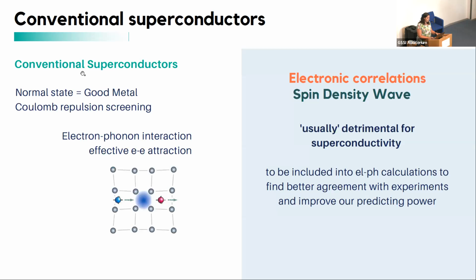So if we look at conventional superconductivity, this emerges by lowering the temperature of a very good metal. There is very good Coulomb screening, you lower the temperature, and you have the electron-phonon interaction that provides the effective attraction. In this respect, electronic correlation, competing order and spin density wave are detrimental for superconductivity, at least in general. And the inclusion of this is extremely important because it will lower our expected theoretical critical temperature and will increase the agreement with experiments and improve our predicting power.